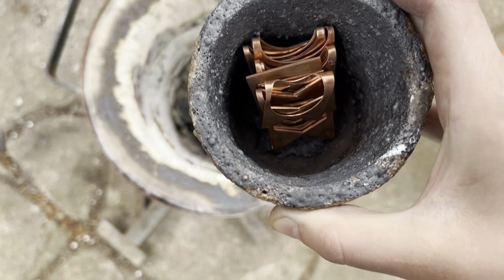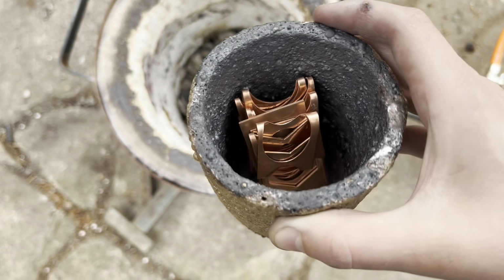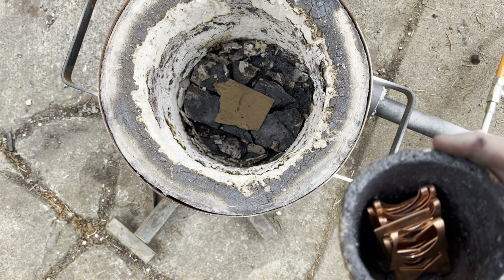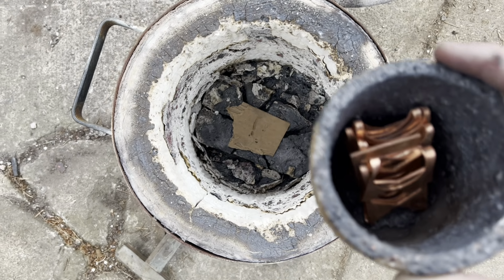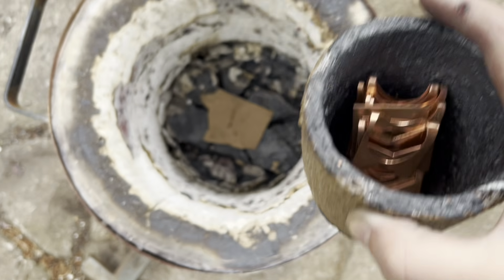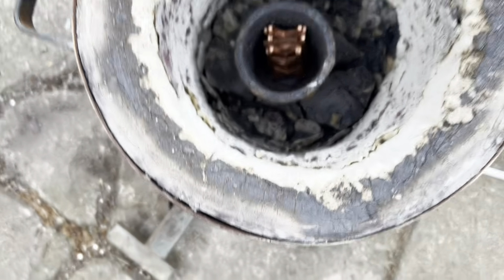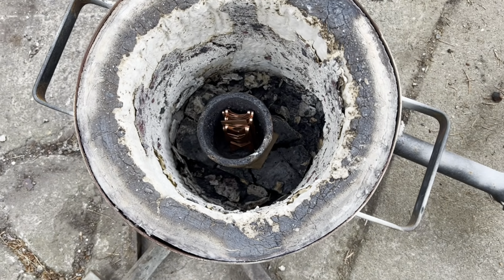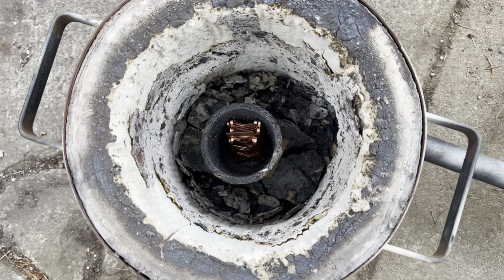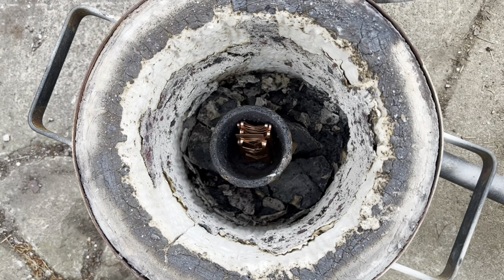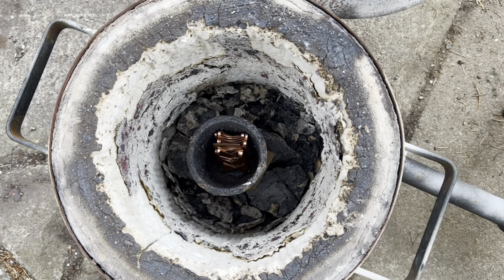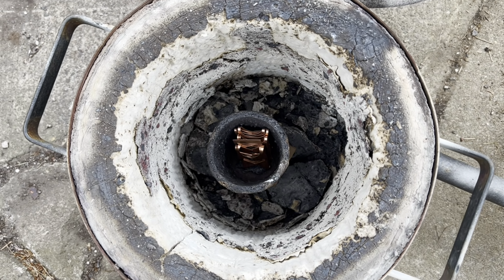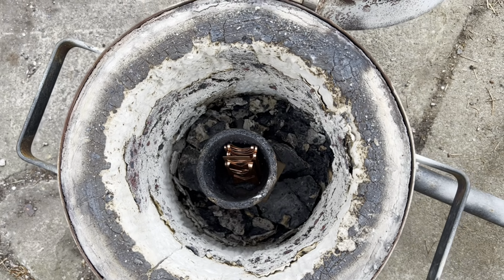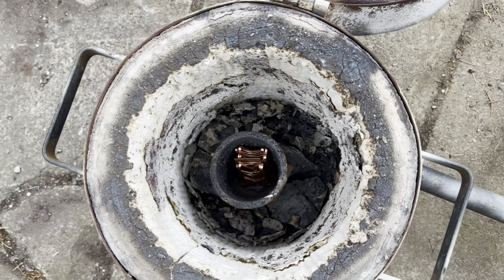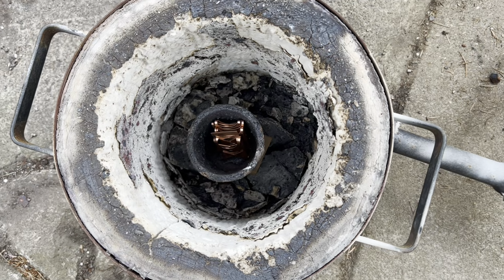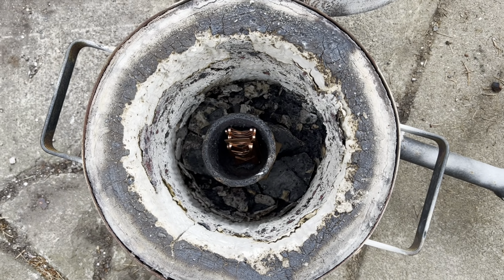I placed our 170 grams of copper inside one of the clay graphite crucibles like I talked about in the crucible tempering video. I also placed a piece of cardboard down to keep this from getting stuck to the fire brick. And as you can probably notice, some of the cement is starting to flake off and the fire brick is cracked. I'd say this furnace has another 2 weeks to maybe a month before I need to reline it and replace the brick. It still works when it's in this condition, it's just the efficiency starts to get a little bit lower. And it just doesn't look good too.